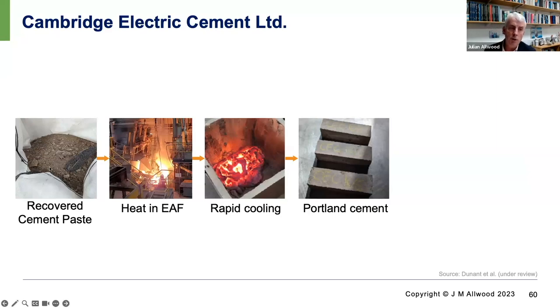What he spotted was that if you crush old concrete and separate out the old stones and sand from it, you're left with something which we call recovered cement paste. And this has virtually the same properties as the flux used in a steel recycling furnace. So instead of adding steel and flux to the electric arc furnace, we now add steel and recovered cement paste. And the cement paste bubbles through the steel as it melts. It doesn't affect the steel making or the furnace lining in the operation. And it creates a slag.